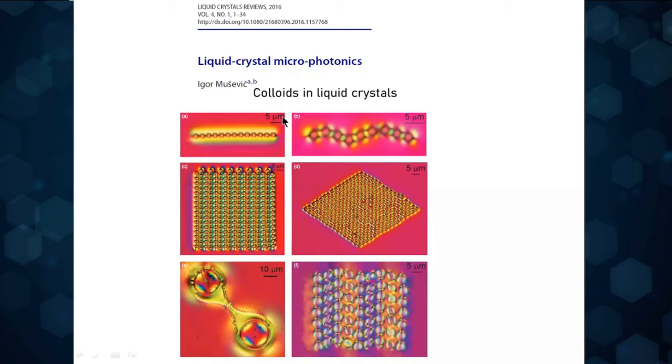These are so-called dipolar colloids, and you can also assemble these colloids in a very interesting wavy fashion, which gives rise to something called quadrupolar colloids. The dipolar and quadrupolar are essentially to do with the topological defects which these crystals actually give rise to. You actually can have combination of sizes of colloids which form an array, and these arrays actually can give rise to very interesting photonic band gaps in such kind of structures, and these are all inside the liquid crystal. So you actually can look at the two-dimensional patterns and assemblies.